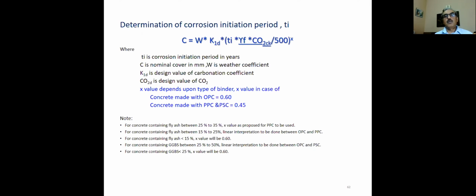So to determine the corrosion initiation period Ti, we have got this equation. From this we can determine the time to initiate corrosion, and added to that the propagation period, we get the total time to cracking, and that should be more than the design service life.